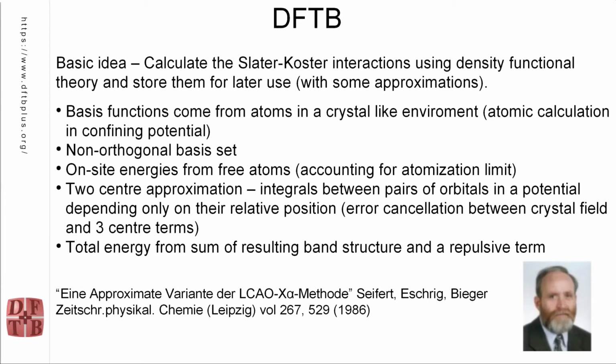So the major features of this are atomic-based orbitals, and I'll show you something in a second to demonstrate what I'm talking about here, which are trapped inside of a confining potential. And you get various terms in the model from atoms. So you have to, for example, account for the limit where these things separate apart if you dissociate a molecule. But when they are closer together and interacting, the calculations are done in a two-center approximation. It turns out that there's some error cancellation between crystal field and three-center terms, which actually makes this quite a good approximation, because there are some things about core states that this deals with in a way that actually ups the accuracy of the resulting calculation. And then you get a total energy from the resulting band structure and, with an idea similar to the solution from Chadi from the 1970s, adding